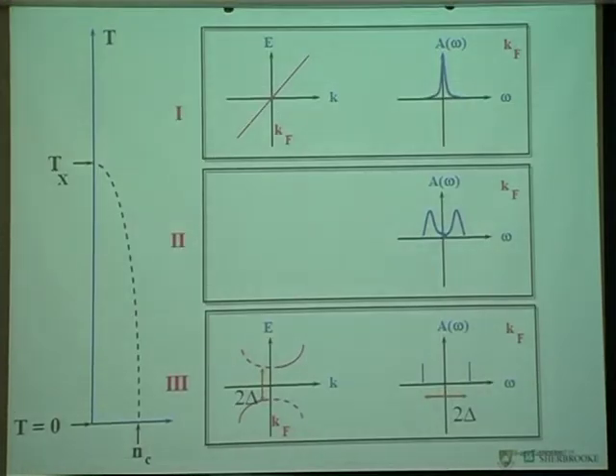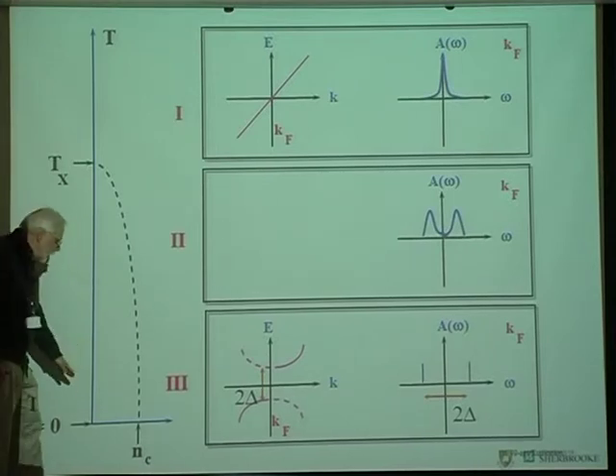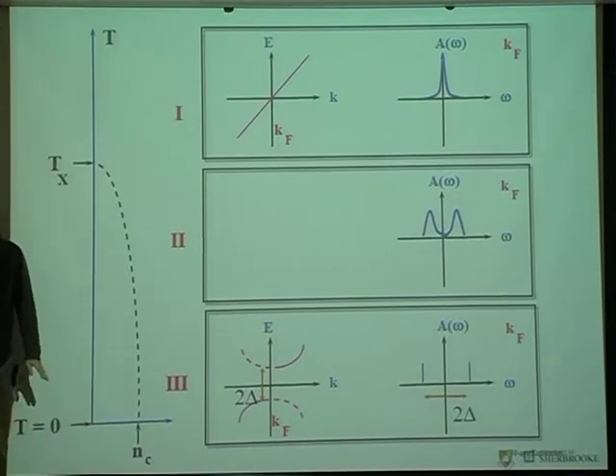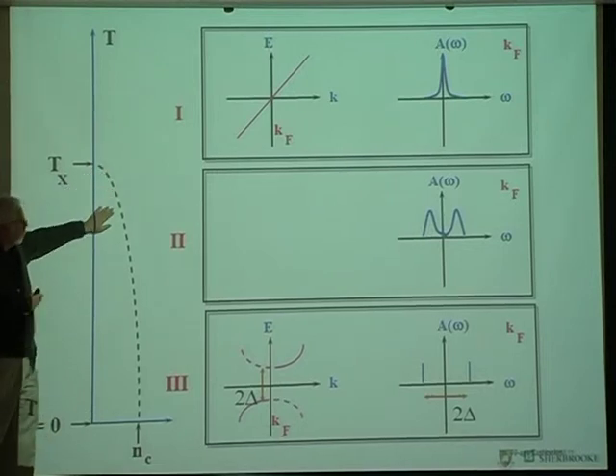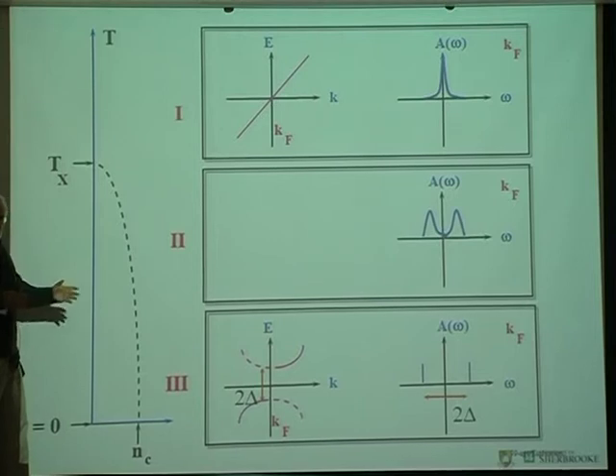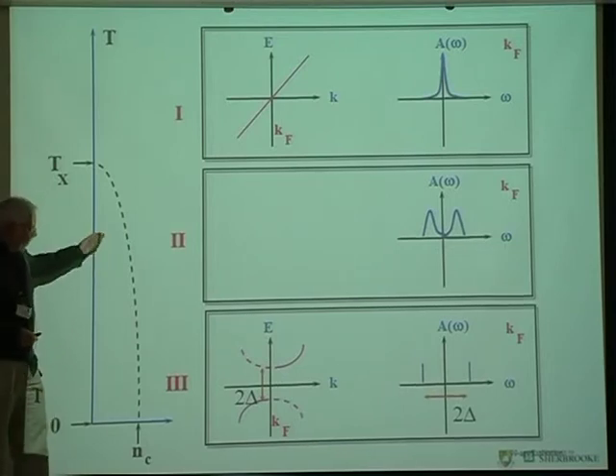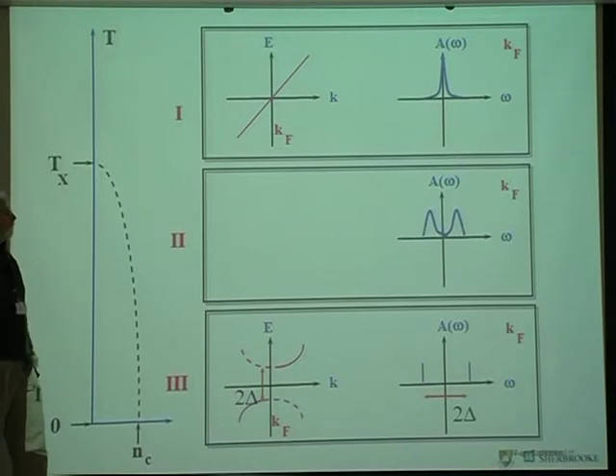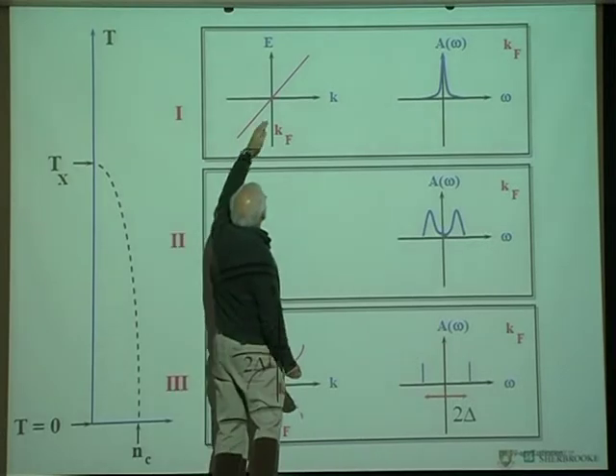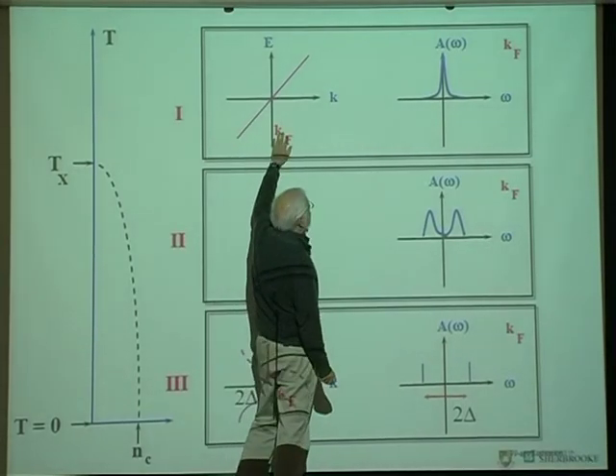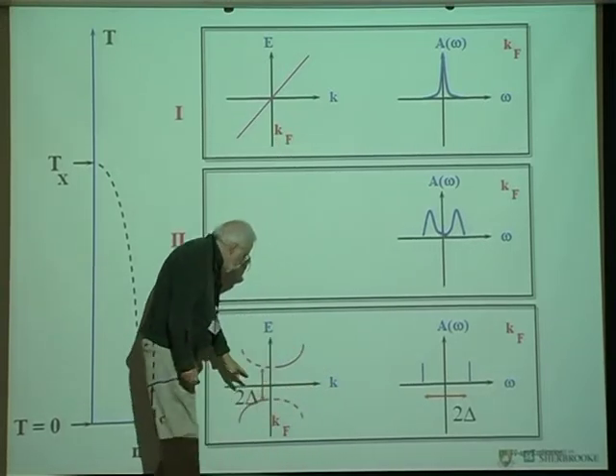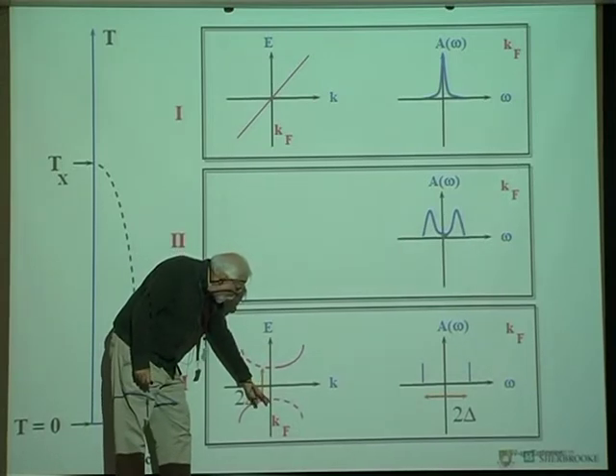Let me skip this. The physics of this is simple to understand. Why do we get this pseudogap? It's because in 2 dimensions we have long-range order really at 0 temperature only, because of the Mermin-Wagner theorem. At finite temperature, nevertheless, we have leftover, if you want, of what would be the mean field transition. So when the correlation length is larger than the thermal de Broglie wavelength, and you look at all the phase space, it's true only in 2 dimensions, you get a precursor of the 0 temperature state, even in the normal state. At high temperature, the energy as a function of wave vector around the Fermi wave vector is just like this. But then in the ordered state, at the antiferromagnetic zone boundary, there's Bragg reflection, and then a gap opens up.